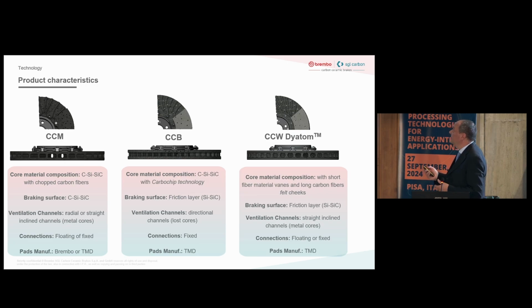These are produced by CVI densification of the preform and then liquid silicon infiltration to obtain the ceramic material. You can work on a complete disc and make the ventilation by machining. But what does it mean? Machining is a cost and is wasting material. Instead, if we can produce the ribs and the ventilation channels directly by molding, we solve the problem of machining. And so this is the idea behind the CCW.